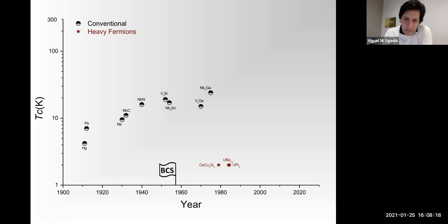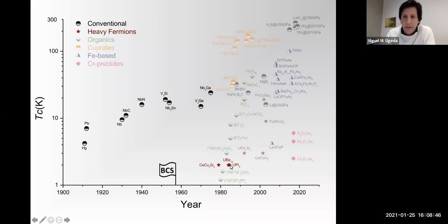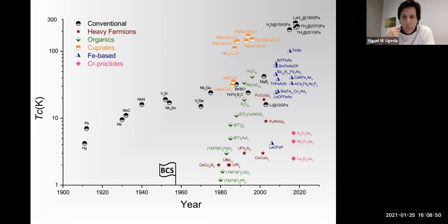But suddenly, this particular material, this heavy fermion compound, was discovered, and shortly after, uranium-based materials were discovered too as superconductors. And it was clear that the superconducting properties of these materials were far from fitting the BCS theory. And actually, shortly after this discovery, a large number of families of superconductors were discovered. To highlight a few, of course, we have the cuprates here with very high critical temperatures. More recently, in 2008, the iron-based superconductors were discovered as well.